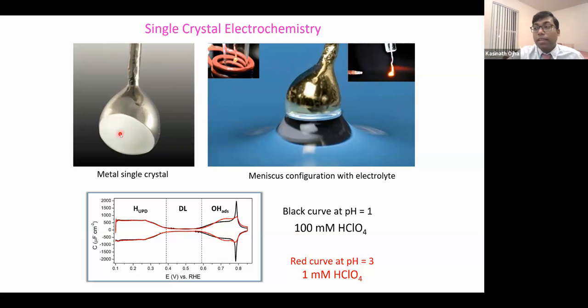And you characterize using HRTEM or STEM to get the facets? STM, we actually do STM to look at the surface. And for platinum, we have very fundamental electrochemistry, and if you do normal electrochemistry, we'll be able to say which facet this surface is, because each facet has a very particular electrochemical signature.